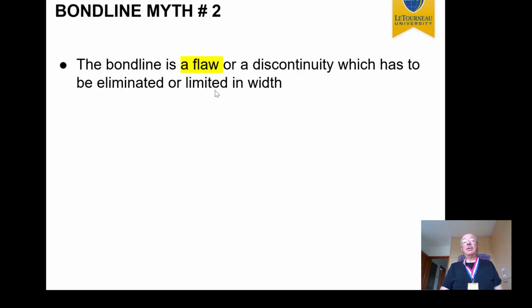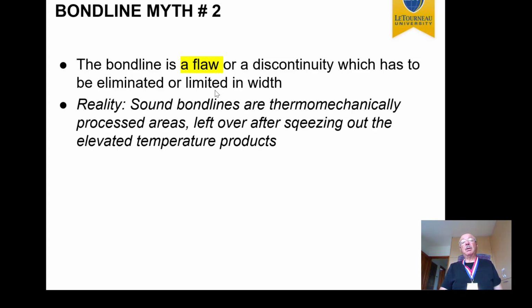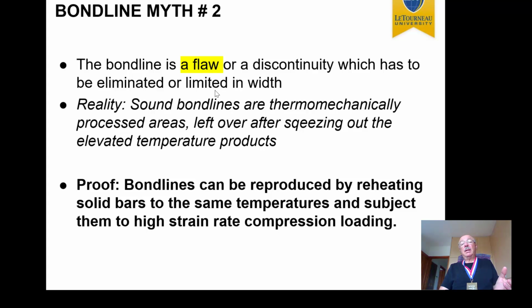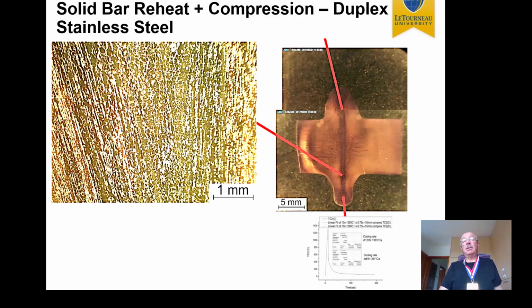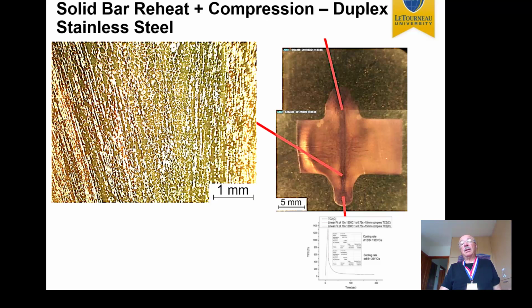The other myth is that the bond line is a flaw and it has to be limited in width or eliminated or whatever. But in reality, sound bond lines are just thermomechanical process areas which were not squeezed out. And so they're not flaws. You can reproduce these by reheating solid bars. And here is a solid bar reheated. This happens to be duplex stainless steel, reheated in the Gleeble and pressed together with high strain rates and high total offset, and we could reproduce perfectly well bond lines without having two pieces together, showing that this is not a flaw. It is just a metallurgical heterogeneity because of the steep thermal cycle and mechanical cycle it experienced.